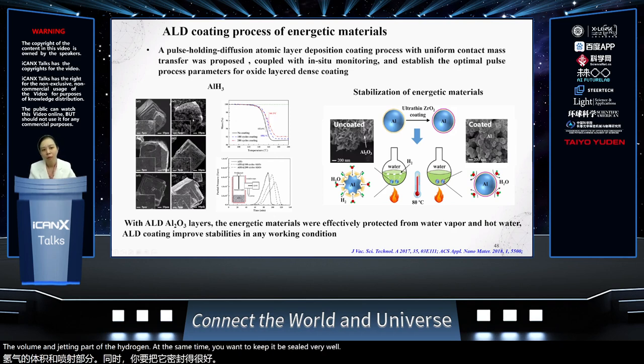So for this kind of thing, we do a low temperature ALD process. If we run it, then you can see the surface will be sort of intact. But if you don't do enough coating, you actually will see the hydrogen release and it leaves holes on the surfaces. And similarly, we can run this for a lot of metal nanoparticles with coatings.